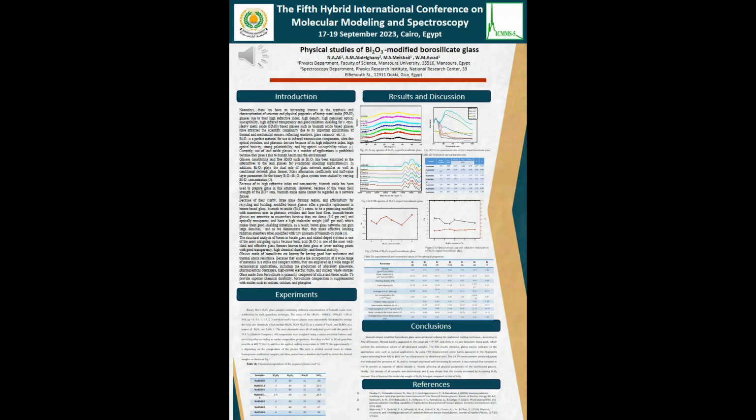Hello everyone, now I will present my research, which is entitled Physical Studies of Bi2O3 Modified Borosilicate Glass. In this research, a glass sample of composition x Bi2O3, 60 B2O3, 10 Na2O, 30-x SiO2, mole percent, was prepared via melting technique. X-ray diffraction technique was applied to prove the amorphous nature of the prepared glasses.